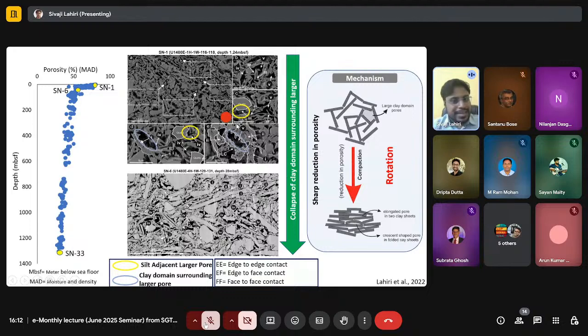And the second type is typical clay domain surrounding larger pore. So here you can see there is a very big pore, and surrounding that there are lots of clay particles. Now I am specifically mentioning these 2 types of pores among all of them because these 2 types of pores are going to play a very critical role with increasing depth to reduce porosity in these samples.